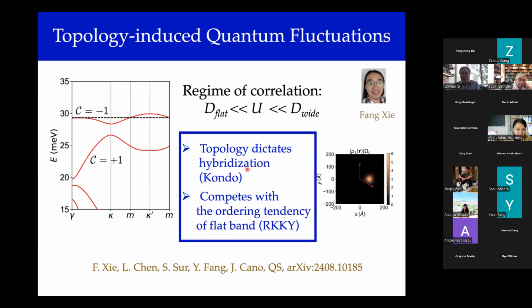Generically, the F-electron materials provide a very good setting for hard magnets. So hard magnets would be the analog of this natural tendency of order. And in fact, there are many more rare earth-based and actinide-based materials which would be ordered, except that for our community, we don't pay particular attention to that. We, in fact, go to the part of parameter space where quantum chemistry dictates that there's hybridization. And then we say, the hybridization-induced quantum fluctuations compete, leading to the Kondo effect, against the ordering tendency. And this Kondo versus RKKY competition realizes the heavy fermion liquid, and in modern times, we realize that strange metal is not too far away.